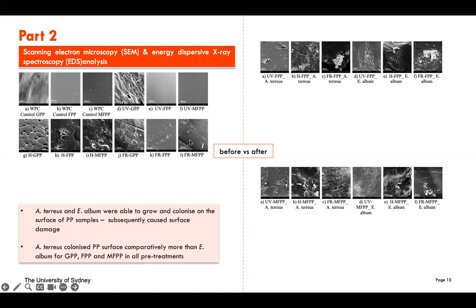So there is some damage that can be observed, but after the incubation with the fungi, you can see much more damage has been done on the surface of each of these polypropylene materials. Okay, so we can see that with the pretreatment, the damage was enhanced. It also indicates that on some of the surfaces there is fungal biomass still attached to them. So it means that these two fungal species are able to attach themselves, penetrate the polymer, and use it as the carbon source.